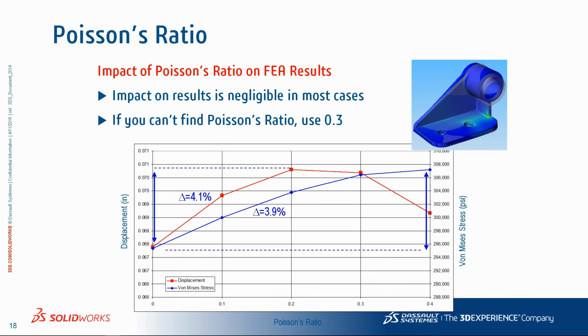The results showed that the displacement and von Mises stress vary by only 4%. So we can conclude that Poisson's ratio has only a small impact on the overall solution, certainly well within the error introduced by local mesh problems. If on top of this, you account for the fact that Poisson's ratio for the vast majority of materials out there is between 0.2 and 0.4, and if you use 0.3 as your default guess, the potential error you're introducing would be 2% at most.